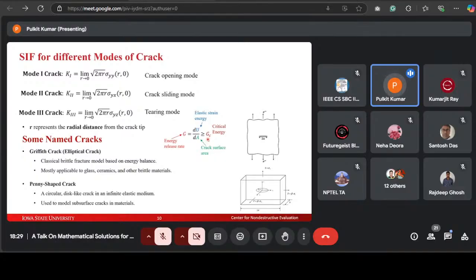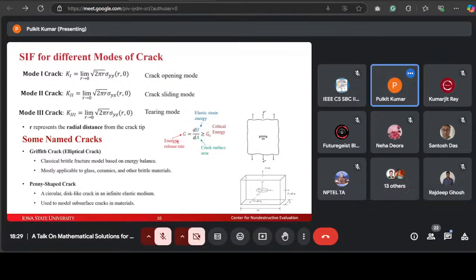Here G is the energy release rate at which the elastic strain energy is released per unit crack area, U is the elastic strain energy stored in the material, A is the crack surface area, and GC is the critical energy release rate or the fracture toughness.